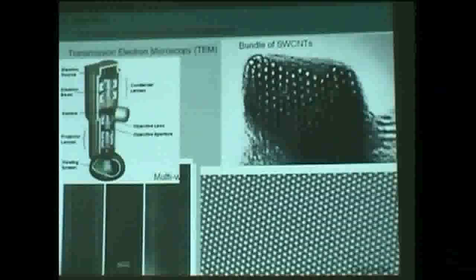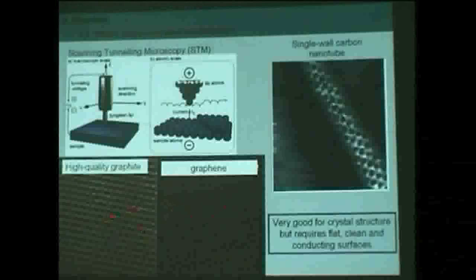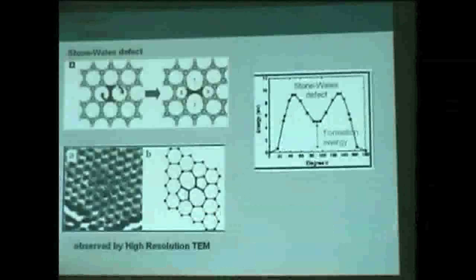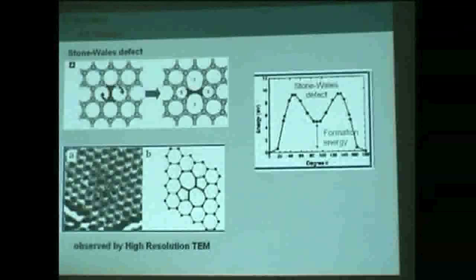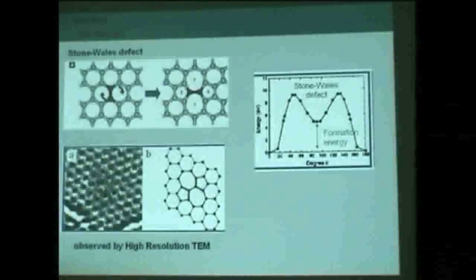TEM is fine, and the other technique which is fine as well is - remember, other technique? STM, scanning tunneling microscopy. Why? Because we also get this nice image, and this is just an area without defects. But there may be areas with defects, and those two techniques, among the ones I presented, are the main two techniques to evidence local defects by imaging them.